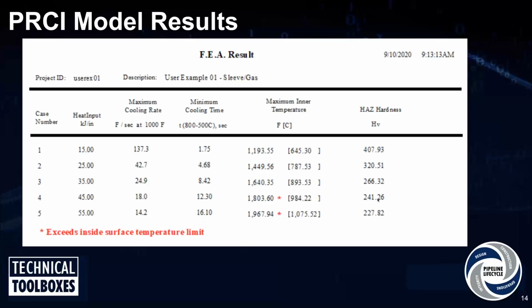Then you input your welding heat inputs, whether it's a welding heat input or your welding parameters. And it'll go through the heating and cooling, and it'll predict your inside surface temperature. And then it'll also predict your weld cooling rate. And then from your weld cooling rate, the model uses published algorithms to predict what that weld hardness would be.